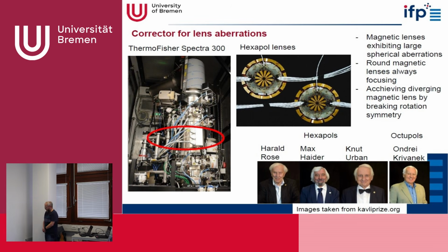Okay, measuring electric fields is in principle possible even for electric fields in between the atoms, but for this we need very, very precise electron probes. And this only is possible because we have correctors for lens aberrations. As I said before, electromagnetic lenses are not very good, because for example, we have a wavelength of 2 picometer, but the resolution is only 65 picometer in our machine. And this also already shows that there are some possibilities to evolve further.